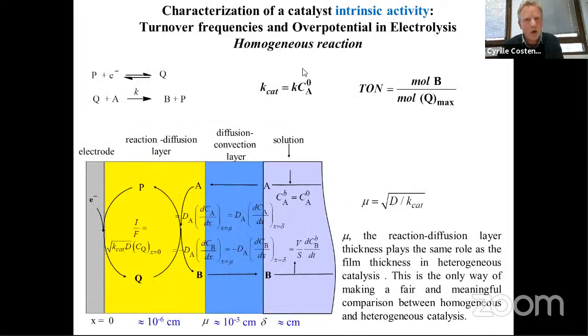Now I will focus on the intrinsic activity. The intrinsic activity of the catalyst is the turnover frequency, and so it is related to what's going on in the diffusion reaction layer in a situation where there is no degradation of the catalyst. And of course, you can relate the amount of product that you accumulate in a solution to the efficiency of the reaction in the diffusion reaction layer.